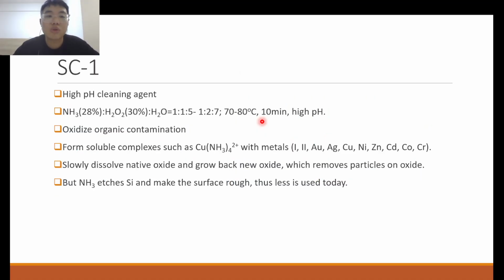So now I'll cover two very common cleaning agents that are often used to remove particles from the wafer surface. The first is SC1. SC1 is basically a high pH cleaning agent. It uses ammonia, H2O2, hydrogen peroxide, and water in a certain ratio. And it's normally conducted at an elevated temperature, not that high, because we are of course limited by the boiling point of water, but basically 70 to 80 degrees. It can be for a certain time, like 10 minutes, and basically the pH is high because of the presence of ammonia.